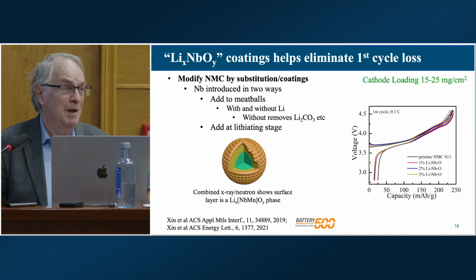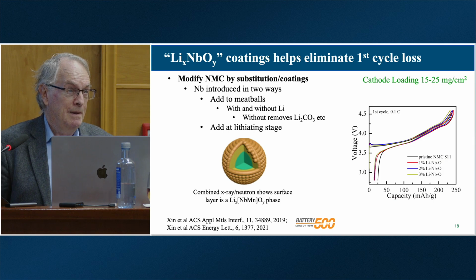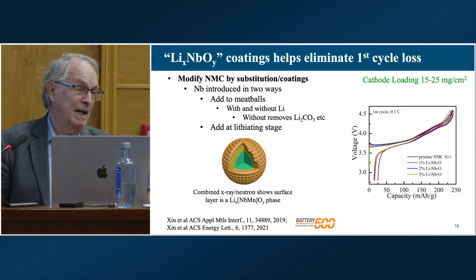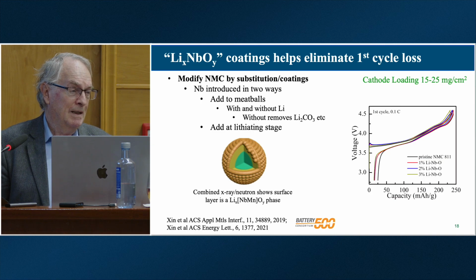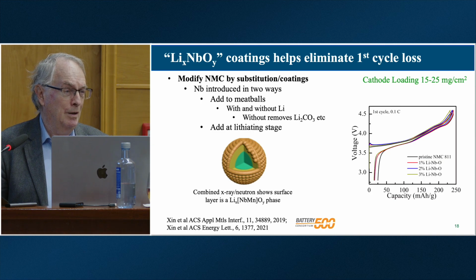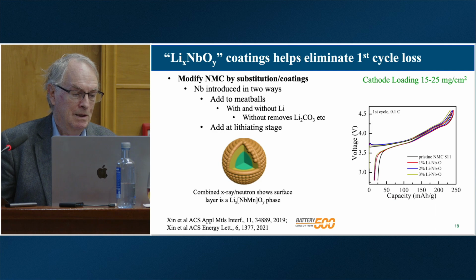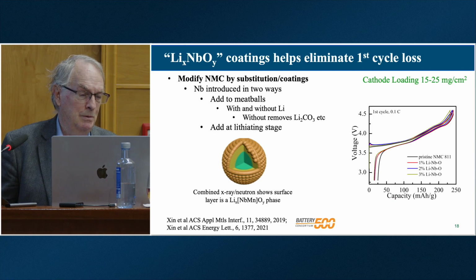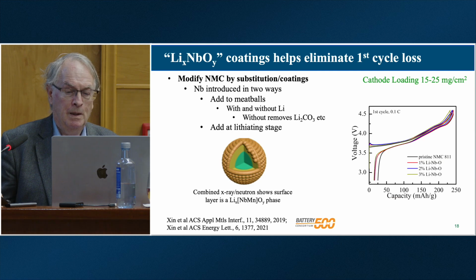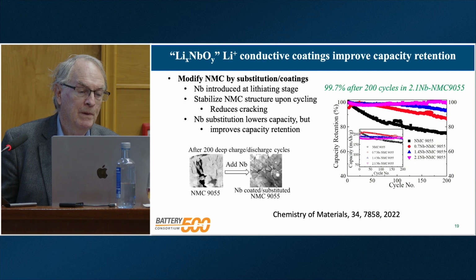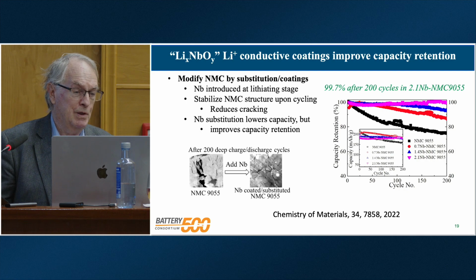It's not a simple coating. Some of the niobium goes into the lattice, ejects some of the manganese, so our actual coating is a mixed lithium niobium manganese oxide. So we're still doing more studies to understand that. But this is showing what a coating can do. If we fire this material up, so we get more of a substitution occurring.